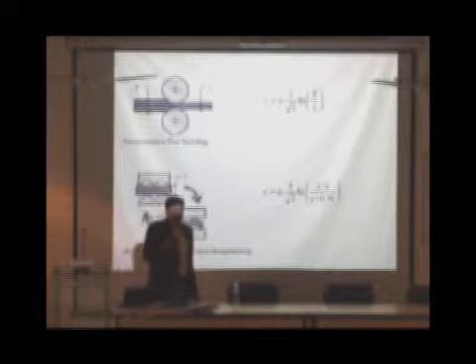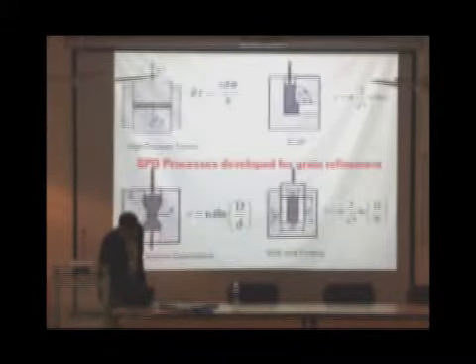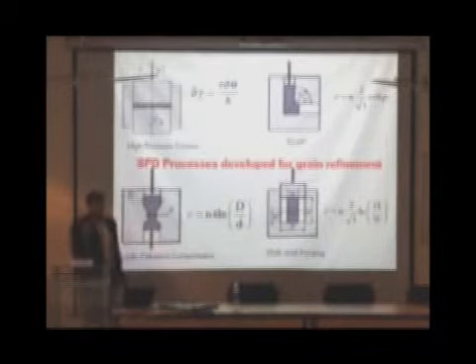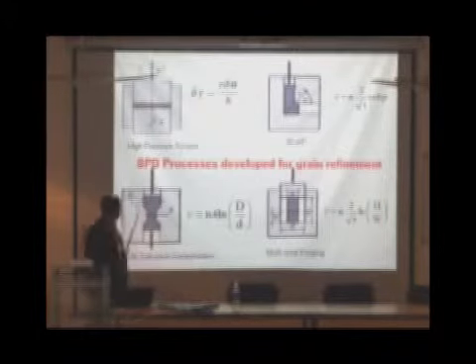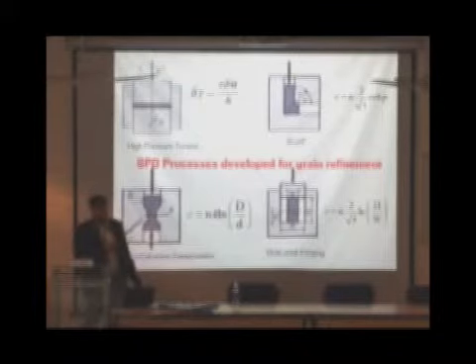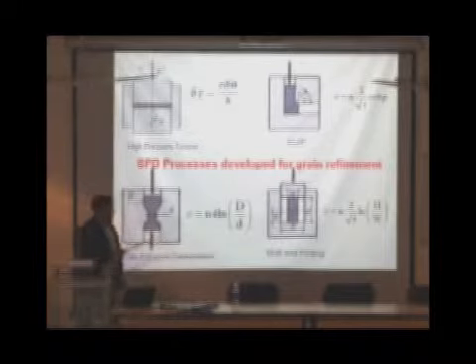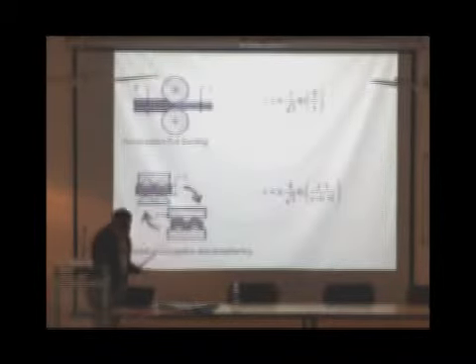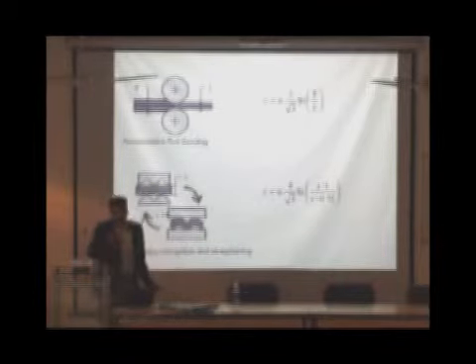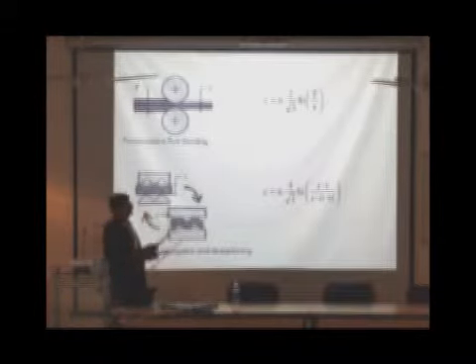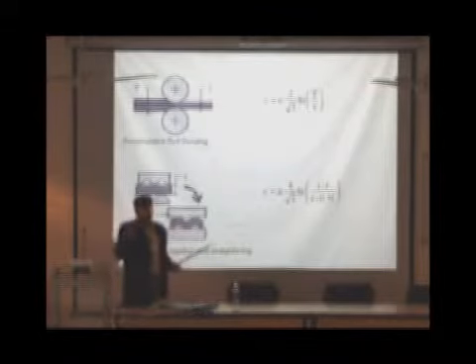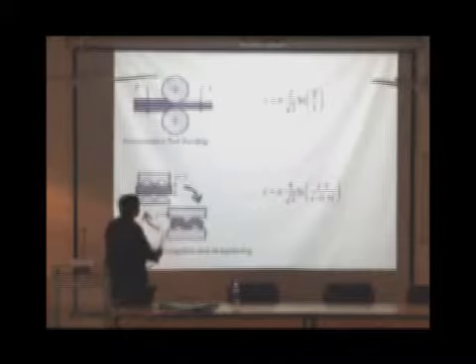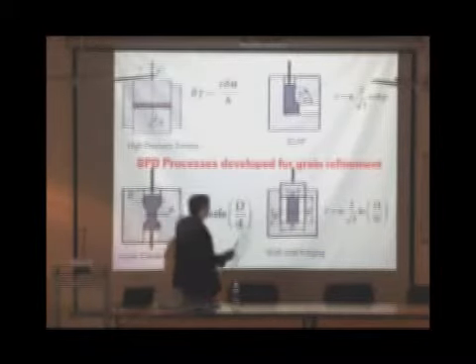Till now there is no commercialization of these processes being done. There is only one process which is showing some kind of commercial viability, that is ECAP process. The problem with HPT is basically the sample size is very small. Same is the case with other processes. We cannot do this process continuously because the main deformation takes place in a discrete manner, not in a continuous manner.